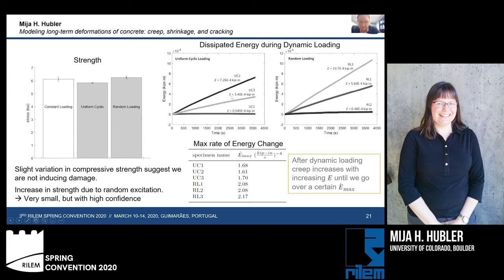Okay, the other thing that we can track during our experiment is the energy dissipation during dynamic loading, as well as the maximum rate of energy change. Relating this data to our creep data, we find that after dynamic loading, creep will increase with increasing amount of energy output into the system up until a point, over a certain point of maximum change of energy that is put into the system. So the rate of change that I'm changing that energy, suddenly I see a decrease in the rate of the creep.